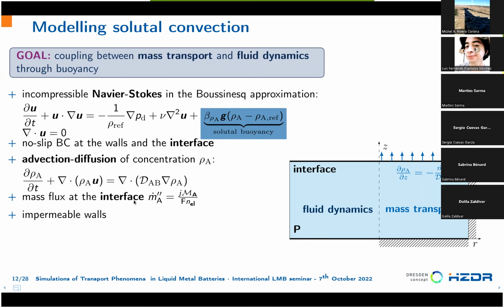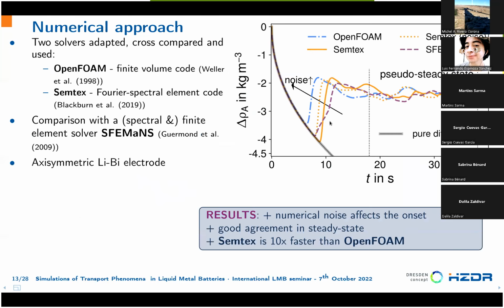We impose at the interface this mass flux as discussed, and the lateral walls are assumed to be impermeable, so no lithium can leak from the lateral walls of the electrode, and all the interfaces are assumed no slip. We will relax this condition for the interface with the molten salt later. It's important to say that now we are only focusing on the bottom layer of the battery, so we are only studying the positive electrode.